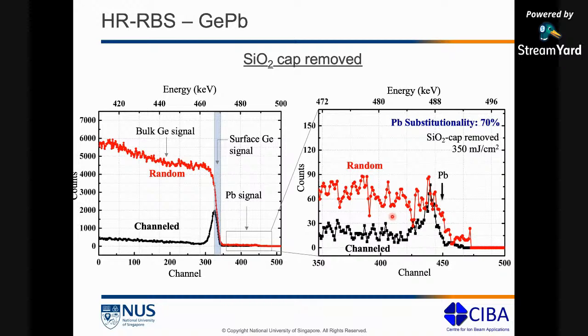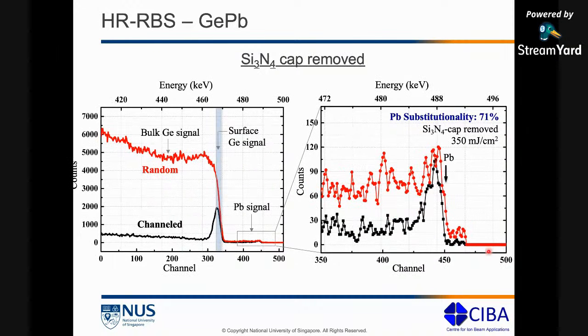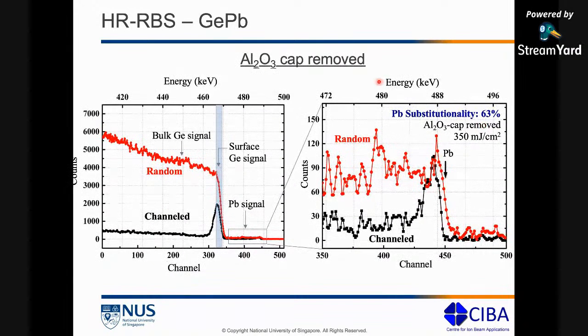We were hoping for more, but 70% was still quite good enough for us. We didn't expect it would be this good. We compared this to silicon nitride. We did the same thing with silicon nitride. So there also we got about 71%, and then this one was the worst of the lot. So aluminum oxide, the substitution behavior was only about 63%.